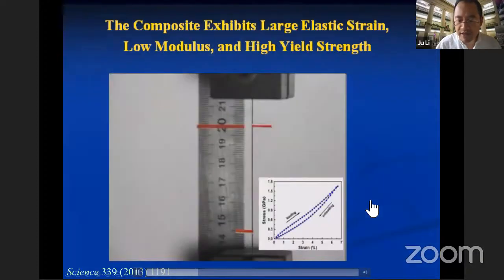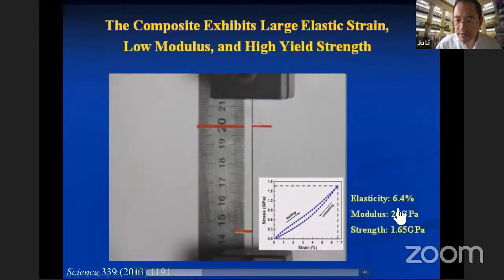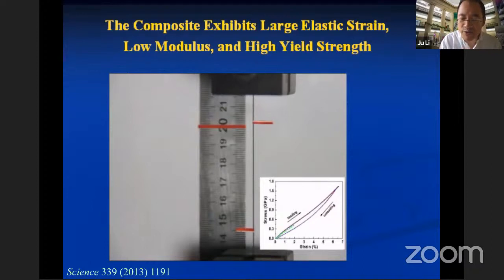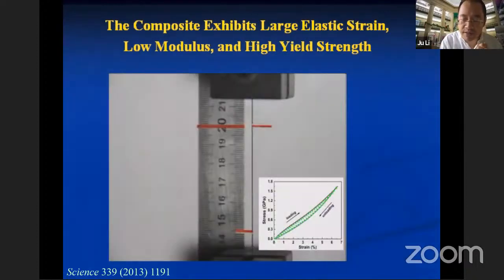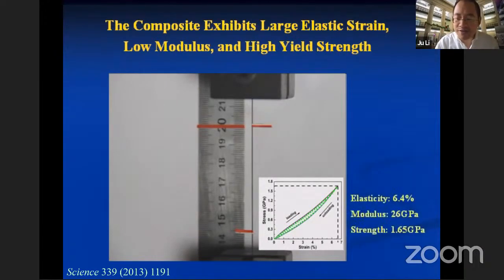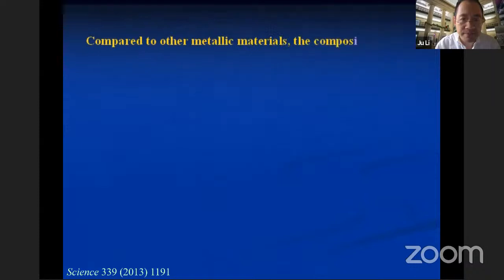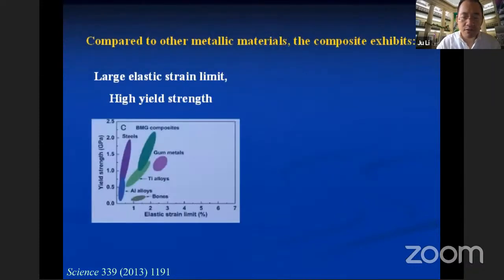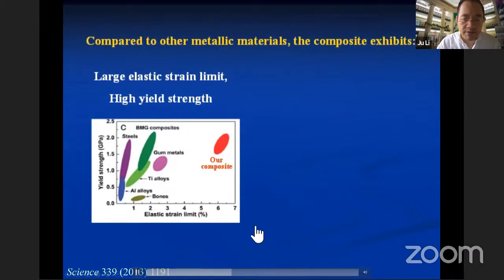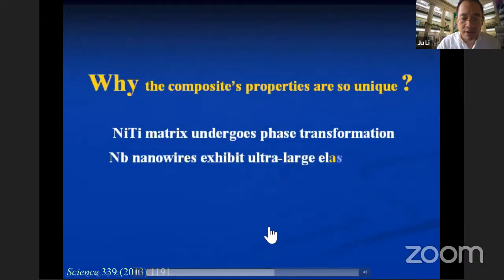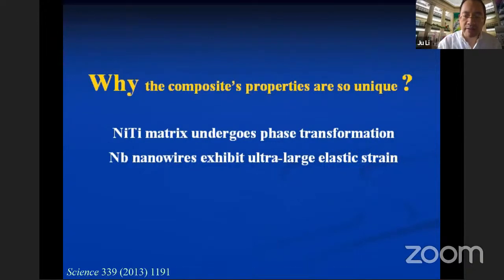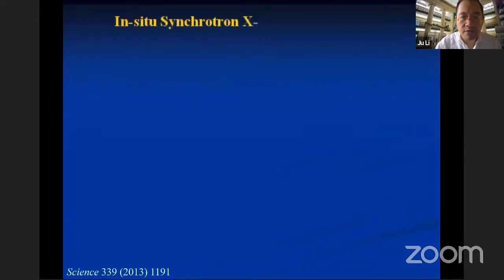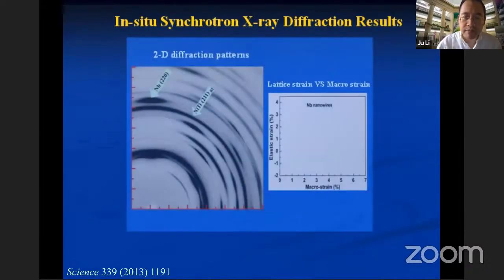It's above 1.5 gigapascal. And the effective modulus is close to that of the human bone, because initially Professor Cui was trying to make this orthopedic material, for the orthopedic implant to prevent the osteoporosis of bones in hip joint replacement. But later he found that actually this is useful for superelasticity. So what is really interesting about this material is that it's kind of in between a polymer and a metal. And just to demonstrate that this is real.